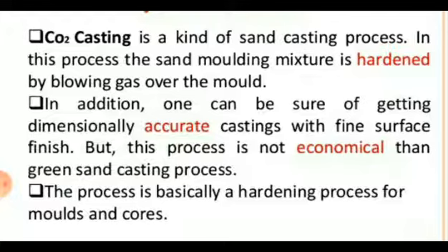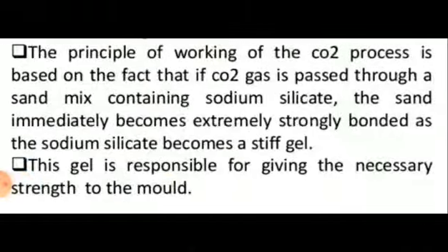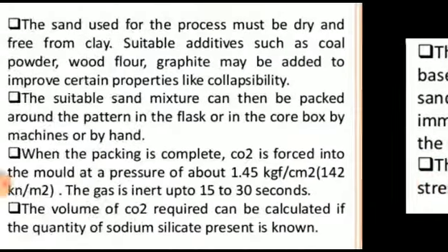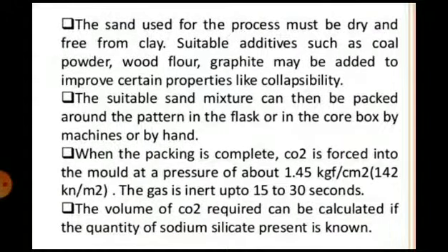The silica sand used must be dry and free of clay. This sand is mixed with sodium silicate liquid base binder in a Muller. So suitable additives like coal powder, wood flour, sea coal, dextrin may be added to improve certain properties.